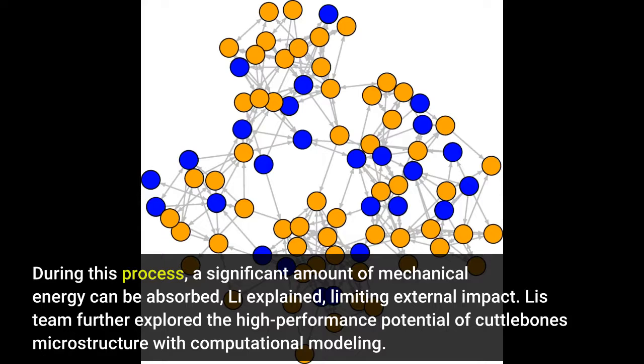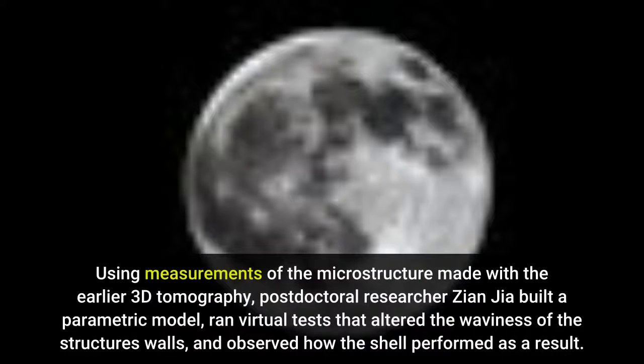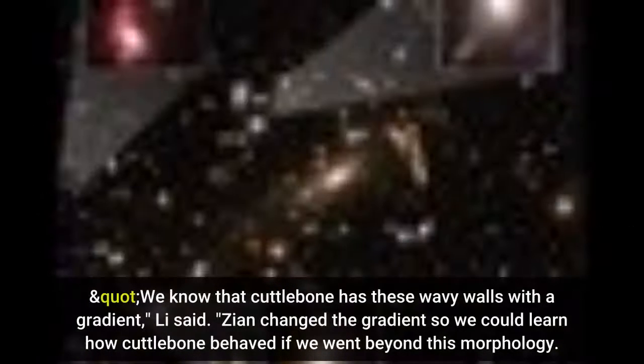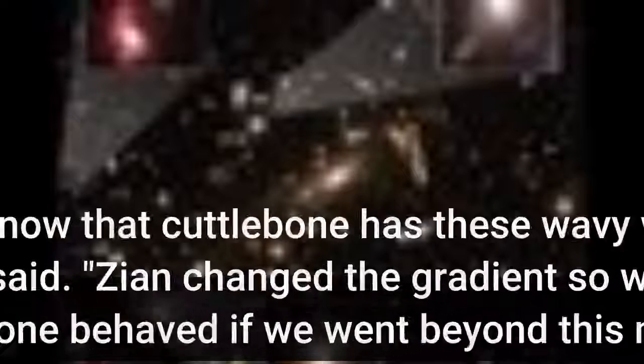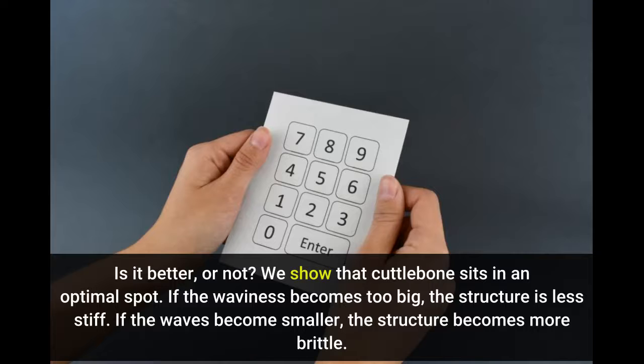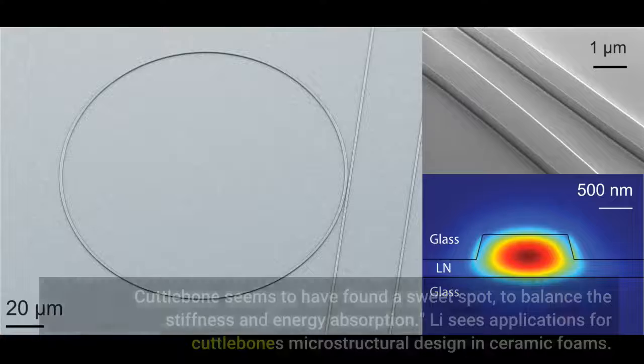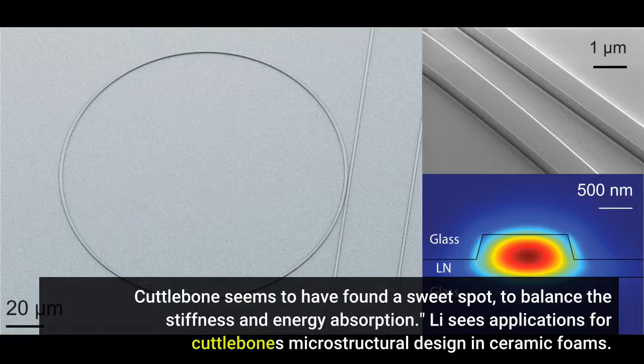Li's team further explored the high-performance potential of Cuttlebone's microstructure with computational modeling. Using measurements of the microstructure made with the earlier 3D tomography, postdoctoral researcher Zian Jia built a parametric model, ran virtual tests that altered the waviness of the structure's walls, and observed how the shell performed as a result. "We know that Cuttlebone has these wavy walls with a gradient," Li said. "Zian changed the gradient so we could learn how Cuttlebone behaved if we went beyond this morphology. Is it better, or not? We show that Cuttlebone sits in an optimal spot. If the waviness becomes too big, the structure is less stiff. If the waves become smaller, the structure becomes more brittle. Cuttlebone seems to have found a sweet spot to balance the stiffness and energy absorption."